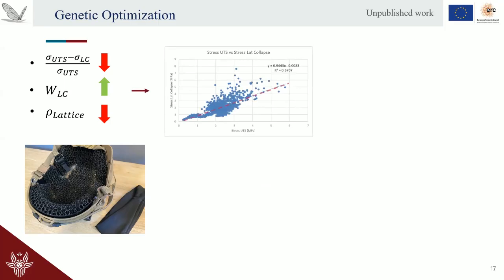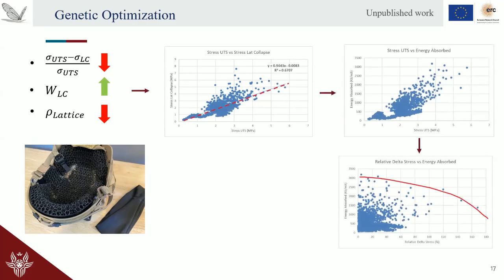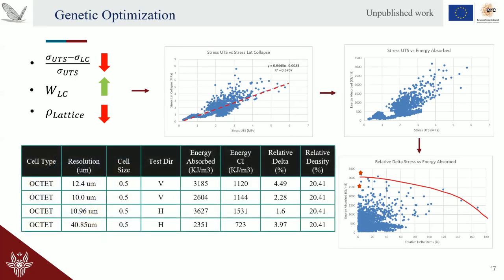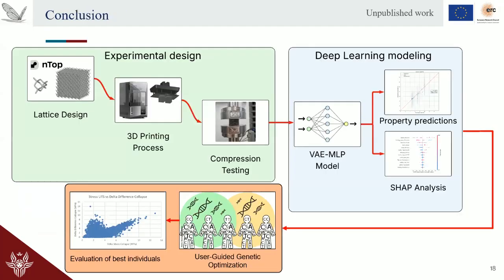So if I start the optimization, I am left with this very nice Pareto frontier. So I can choose two points of interest that in this case are maximizing the energy absorbed and minimizing the drop. And I'm left with those very nice values for both topology and print parameters. Those parameters are optimized, of course, for my printer, for my resin, and this case study. But if you apply this methodology to your work, you will find, of course, different coefficients, but it will work because this methodology that I just presented is very robust.